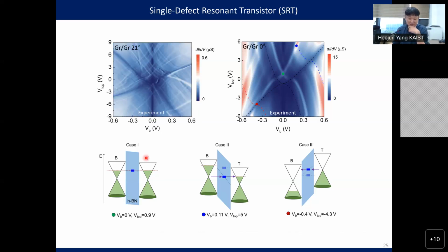Okay, but if we use some general graphene layer without our intentional lattice matching, for example, 21 degree, this is intentionally made. We have some very, very different things because we have some random resonant tunneling. Of course, we see an X-shape. They are from graphene's Dirac point, which is quite robust. Whatever the momentum is, we can see. But another thing here,